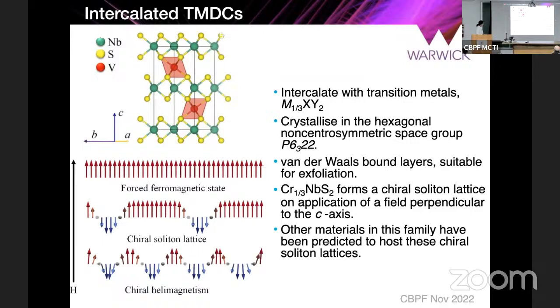So for the chiral soliton lattice, we need a chiral helimagnetic ground state. And if you apply a field perpendicular to the c-axis, in some of these materials like the chromium niobium sulfide, you see the formation of a chiral soliton lattice. And as you increase the field, you find these regions of the ferromagnetically aligned spins gradually increasing until finally they go into the forced ferromagnetic state. So this is the interest in these materials.